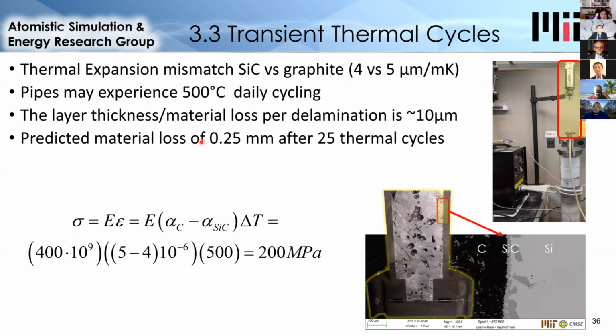One other issue we investigated was the effect of just transient thermal cycling, so heating and cooling of a single material, which is relatively spatially uniform. The reason this might cause a problem is that silicon carbide and graphite have different thermal expansion coefficients. So silicon carbide expands less with temperature. So when the system is heated, silicon carbide is loaded in tension, and because of the 500-degree temperature gradient, this results in a stress of about 200 megapascals, which is greater than the tensile stress of silicon carbide.